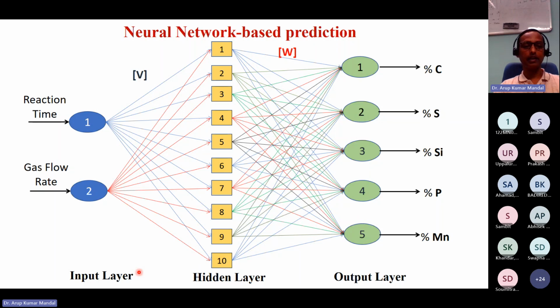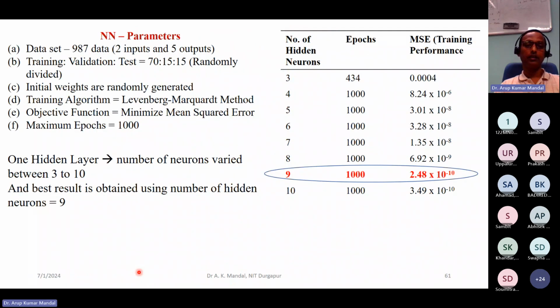Here, the reaction time and gas flow rate are the inputs, and carbon, silicon, sulfur, phosphorus, and manganese are the outputs. We have taken 987 data sets, with 2 inputs and 5 outputs. Training, validation and test sets were randomly divided in the ratio 70 to 15 to 15. Initial weights are randomly generated from this equation, and as the training algorithm we have taken the LM method, and the maximum epochs taken under consideration is 1000.